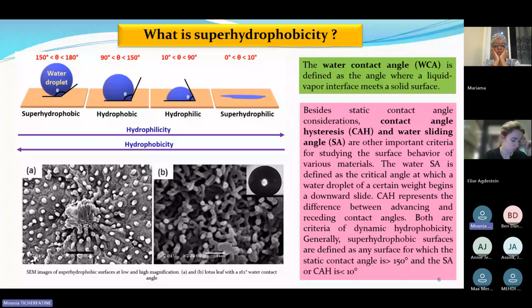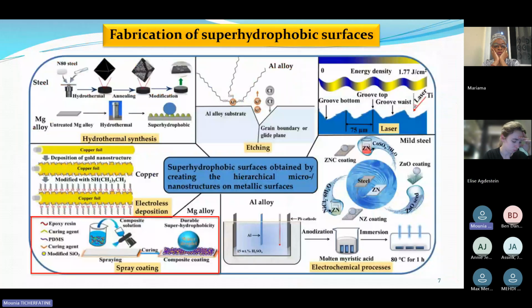Now, how is this superhydrophobic surface fabricated? Surface chemical composition and surface roughness are the key factors contributing to the formation of superhydrophobic surfaces. There are many methods and techniques to create roughness, followed by modification to achieve superhydrophobic surfaces, such as templating, etching, hydrothermal synthesis, anodization, electrodeposition, and most importantly nanocomposite spray coating. Nanocomposite spray coating offers a cost-effective method for creating superhydrophobic surfaces. By using advanced nanomaterials, this technique achieves high-performance water repellency at a low cost compared to the other methods. It provides an efficient and economical solution for developing durable hydrophobic coatings across various applications.